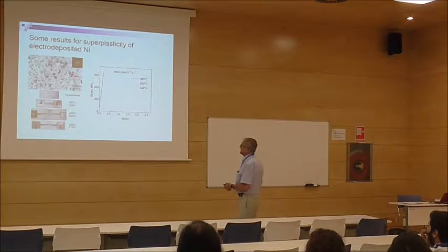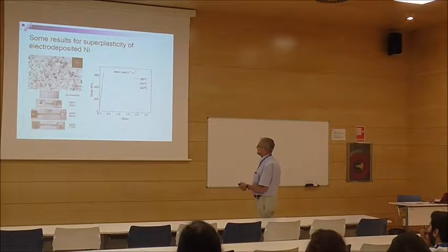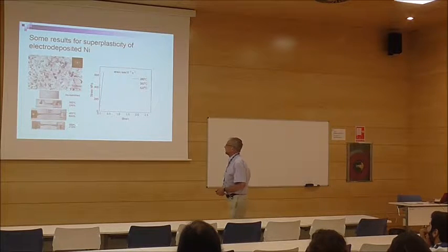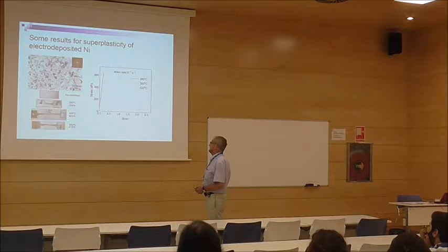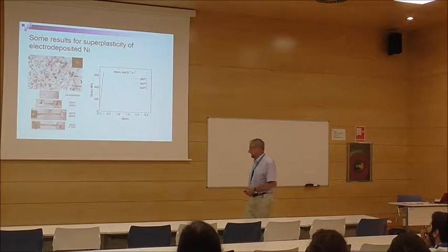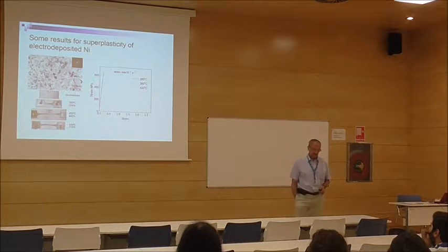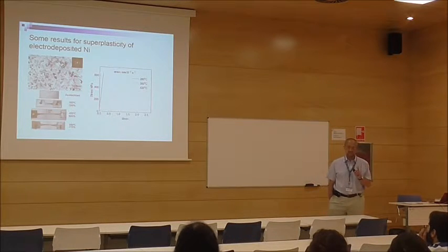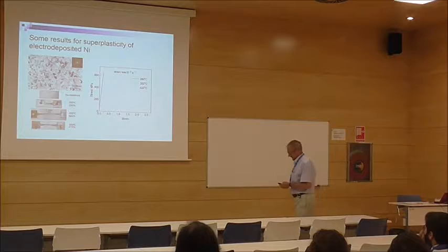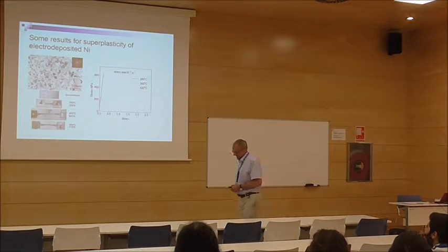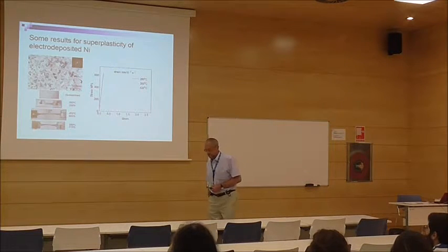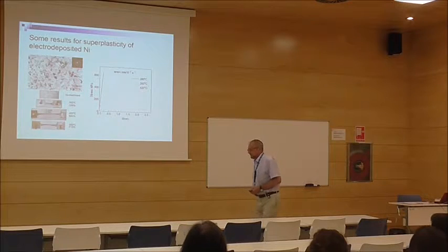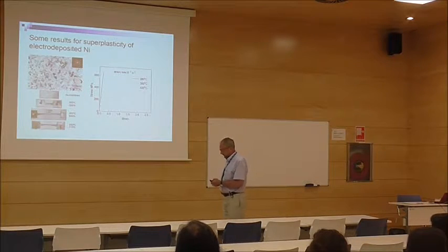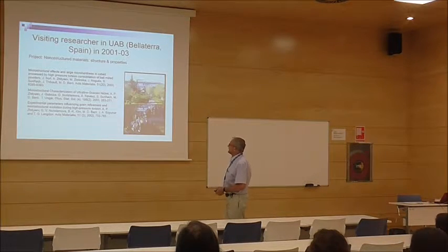So this is just a picture from this electrodeposited nickel. You see, we got almost 900% at 420 degrees C. It was a world record at that time for pure metals. Remember, it's pure metals, because usually people say it's impossible, during grain growth, to obtain superplastic behavior in pure metals.